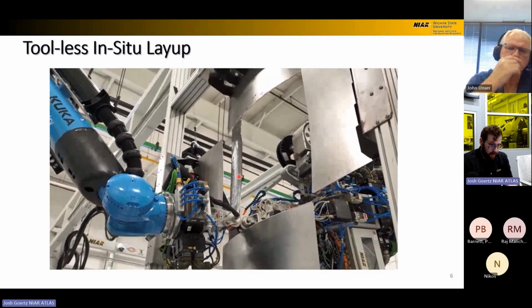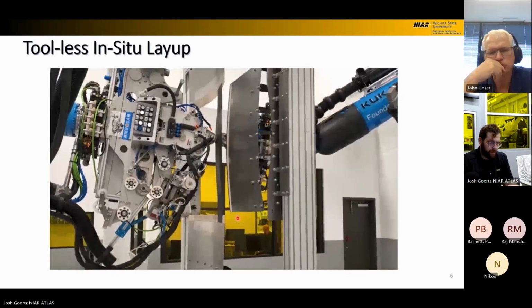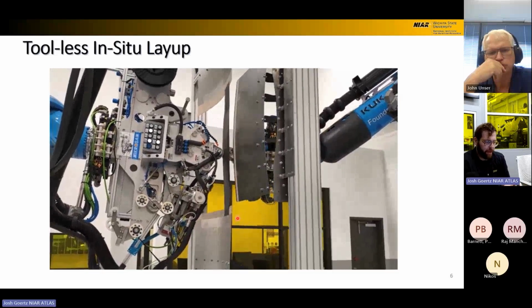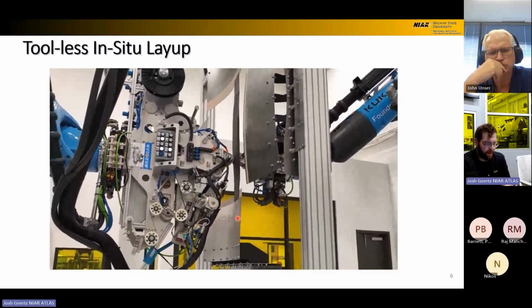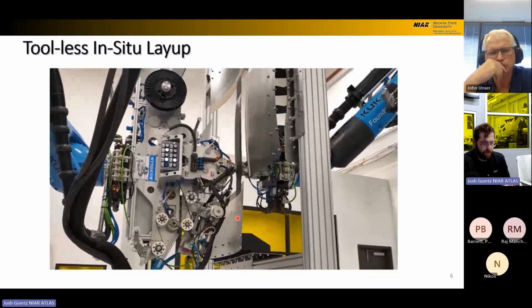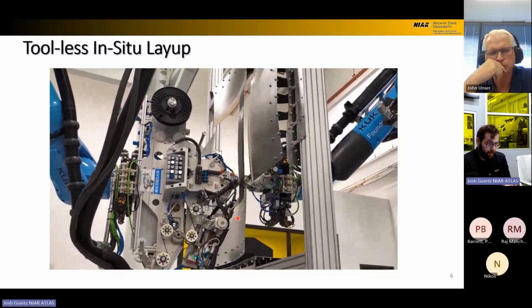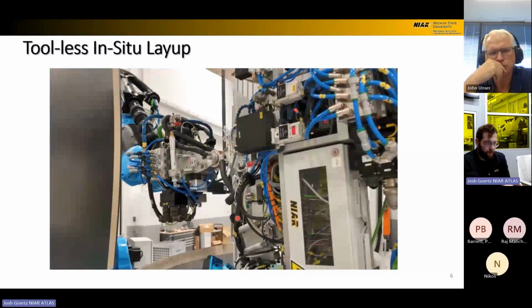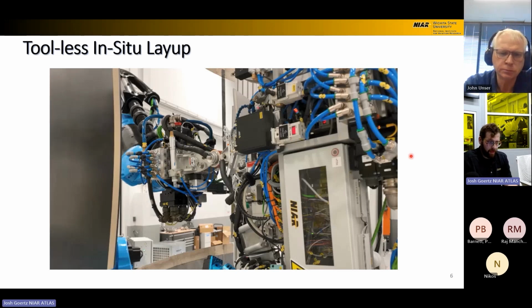On this first ply here, to get the structural rigidity of the first ply, we actually overlap course to course for that first ply by 2/3 of the course width. That prevents the tows from wandering out side to side as we're doing this layup. It does mean that for this particular part, we end up with 3 0-degree plies when we start the panel. So that is the only one of these machines in the world currently that can do this toolless manufacturing.